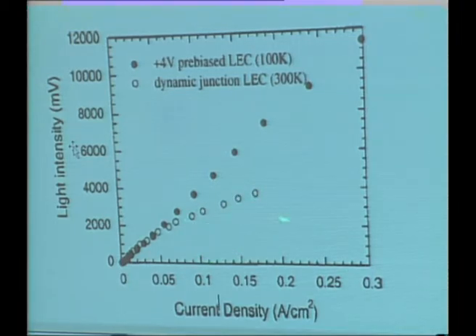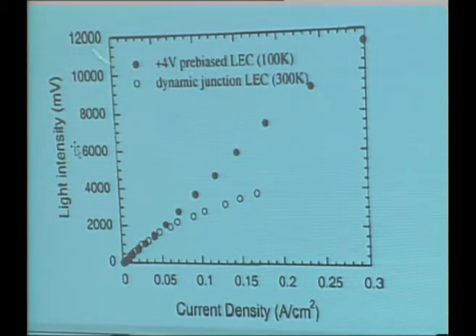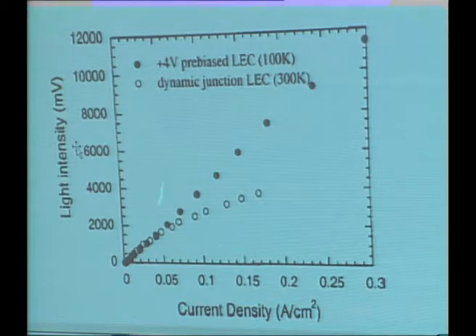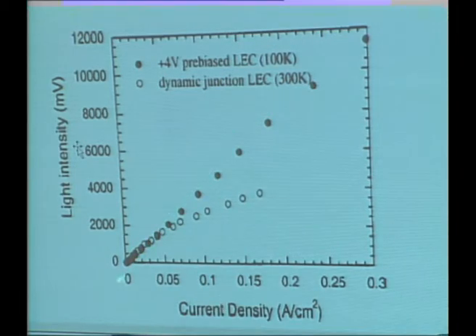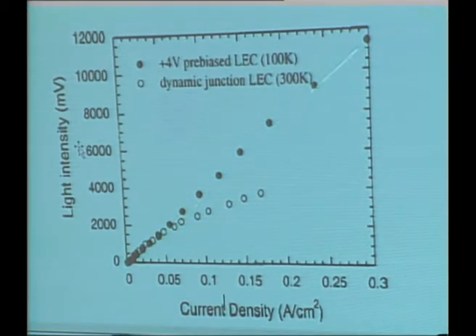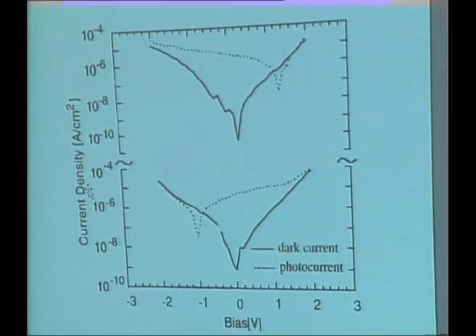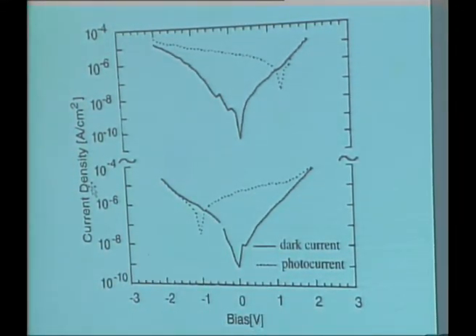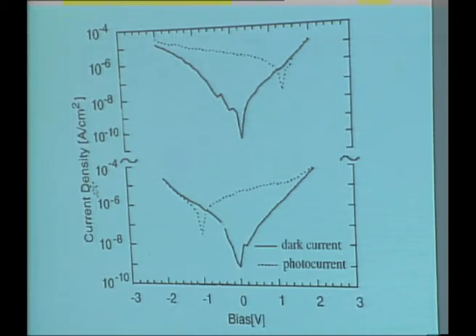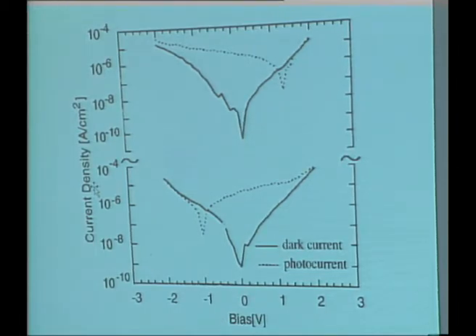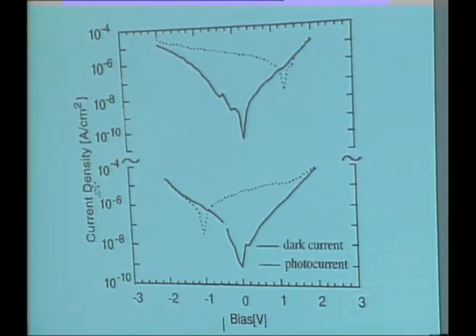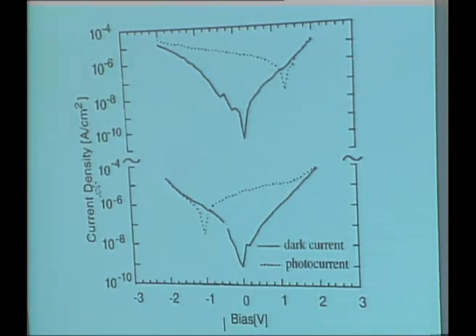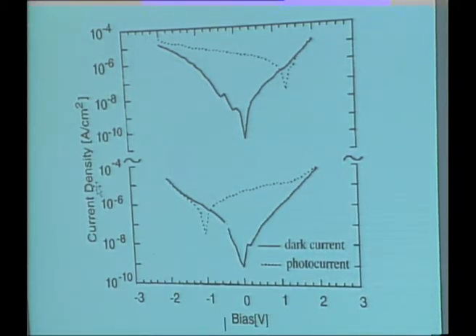At room temperature, it just won't go and it's starting to fail. This, by the way, is not reversible. But if you freeze the junction and cool it down to 100 degrees Kelvin, you can drive much higher currents, and you can do that in a reversible way. So the thing works. And this is the classic proof that you've got this built-in junction.